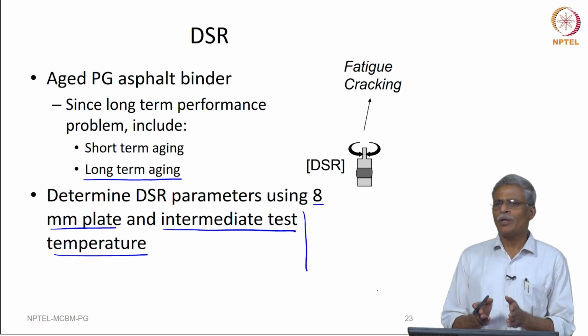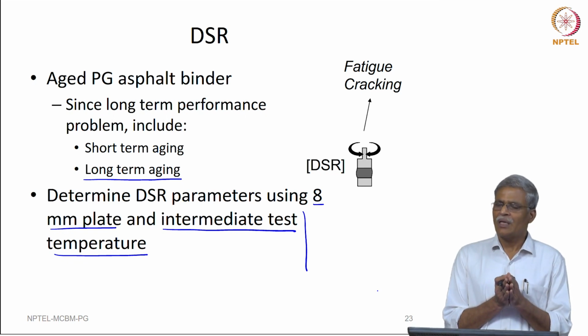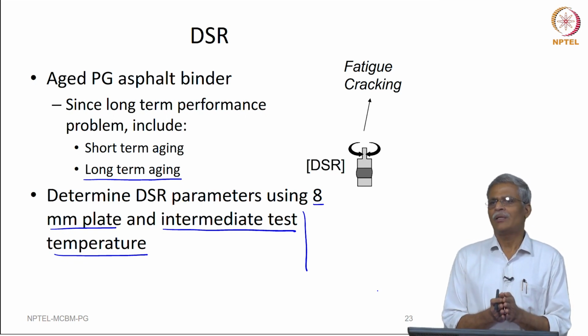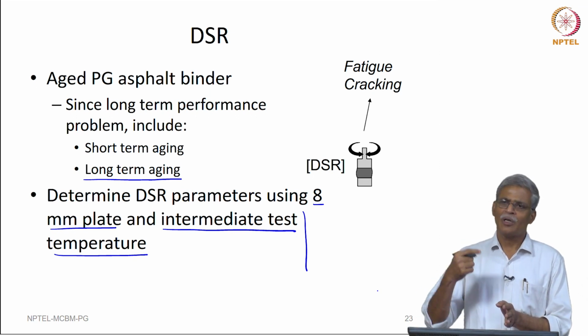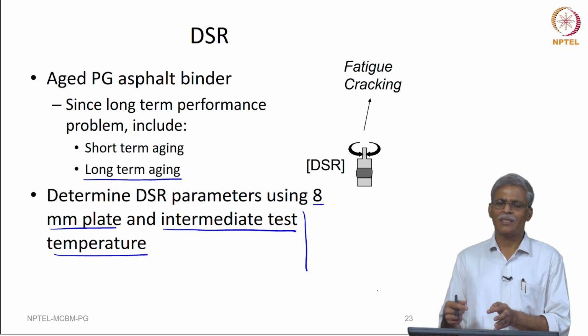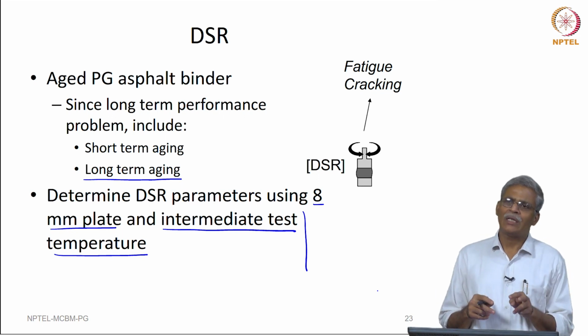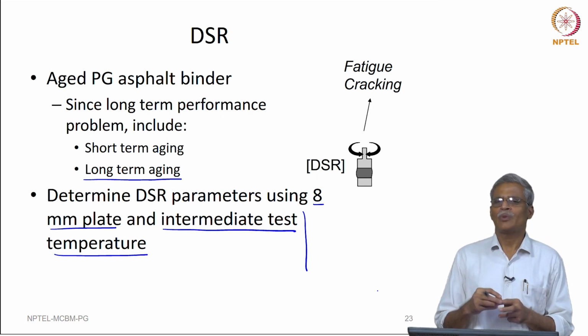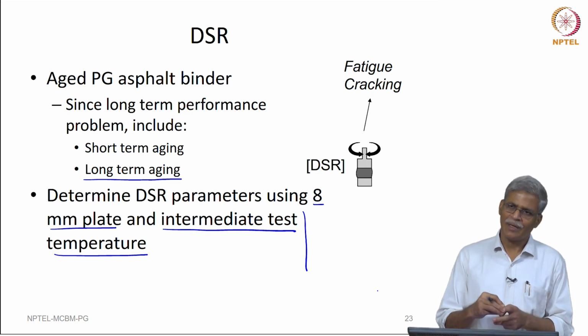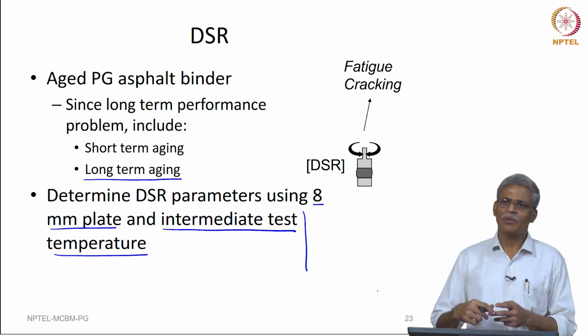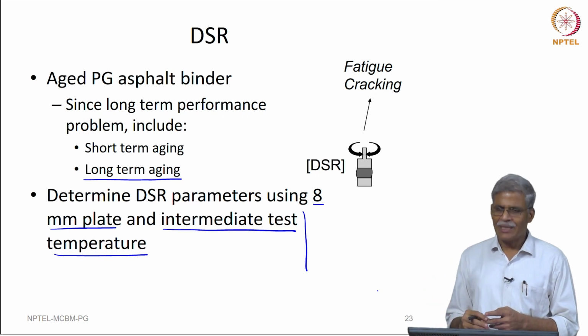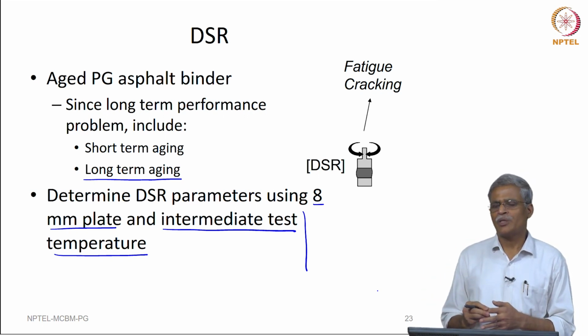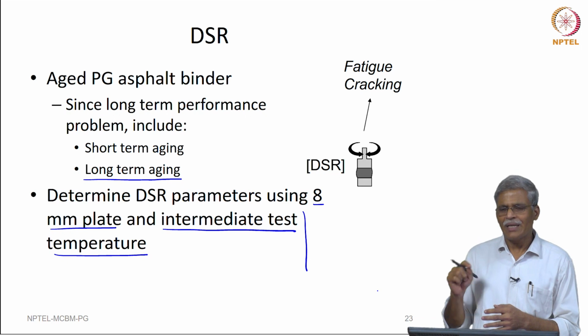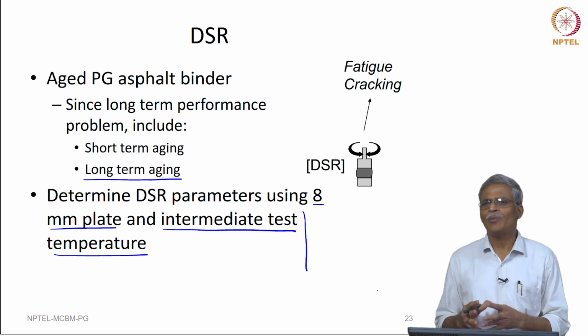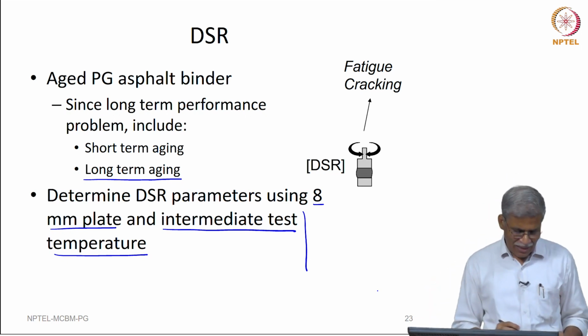So, what we now need to do is to take the unaged binder, do a DSR test on the unaged binder, short term age the binder, and do the DSR test again. These two tests will tell you some idea about the specification parameters required for rutting. Now, from the short term aged material, do a long term aging test, and then on the long term aged material, again carry out a DSR test, and that will give you some idea about the expected fatigue damage of the material.